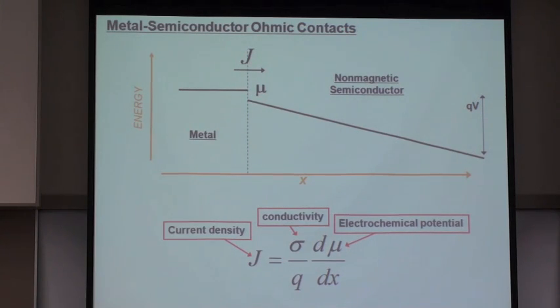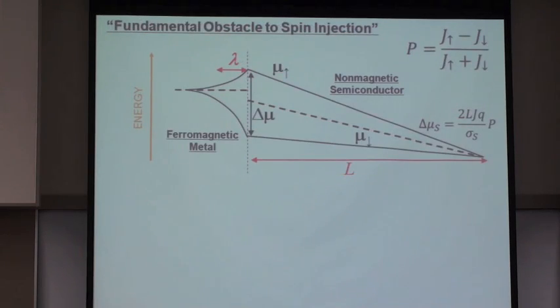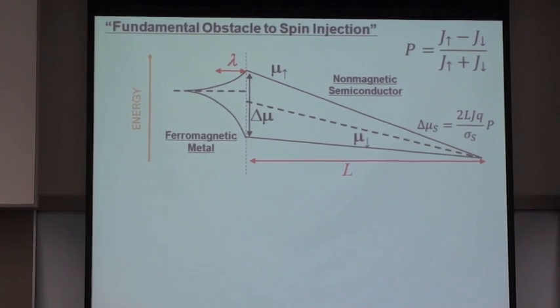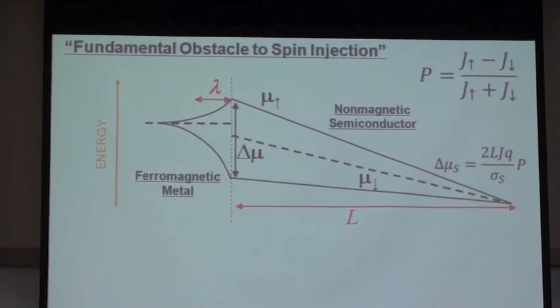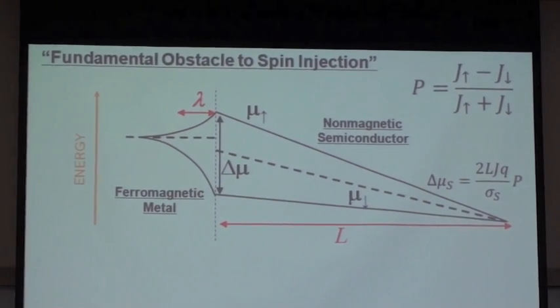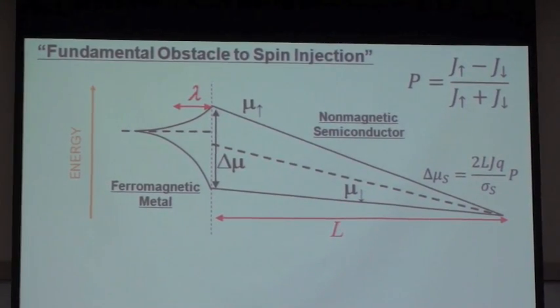And so, because you have a difference in the conductivities, you can see that we have a higher slope, higher gradient of electrochemical potential in the semiconductor as compared to the metal. Okay, so basically what this means is that when we apply a voltage, we get almost all the voltage drop across the semiconductor. Now, what happens when we have a ferromagnetic metal? Again, we want to use this as our source for spin injection. Well, what happens, of course, is that if we want more spin-up electrons to flow in the semiconductor than spin down, then because the conductivity of the non-magnetic semiconductor is exactly the same for spin-up and spin-down, the electrochemical potential gradient has to be different.